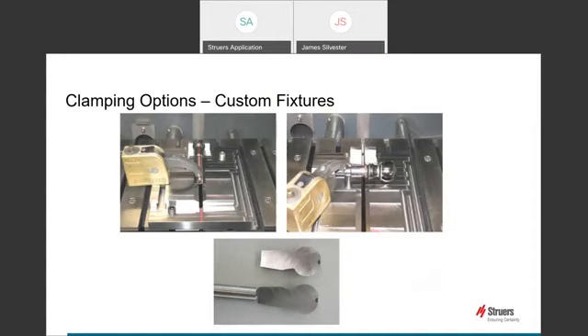This sample caused particular problems as it has no available straight edges, very small cross sections and complex geometry. A longitudinal section was required through the ball end into the stem. The full length of the stem was not required. A plate was made with cutouts and depressions to locate the part and allow the use of a single vertical clamp to keep the sample in position during cutting.